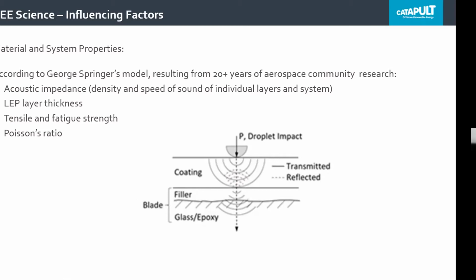When it hits an interface, if the energy hasn't been absorbed by your LEP, you get a reflected wave back into your LEP system, which will doubly load the amount of stress your LEP is seeing. The same thing goes if you have voids in the system, or particles, like the titanium dioxide I mentioned. These cause lots of little reflections and reduce the damping efficiency of the system you're creating. So George Springer said the key material properties are the acoustic impedance, the layer thickness of the LEP, the tensile and fatigue strength of your LEP, and the Poisson's ratio.